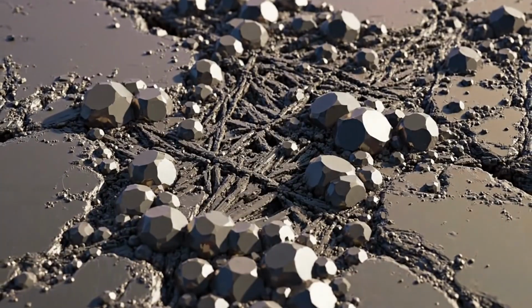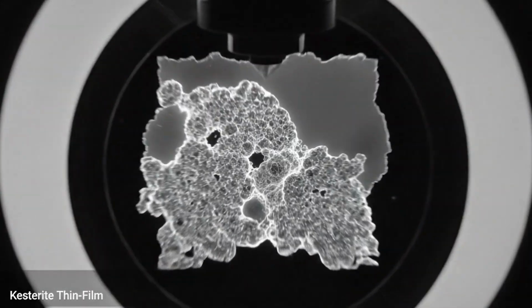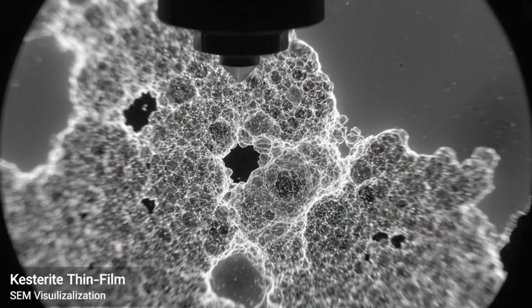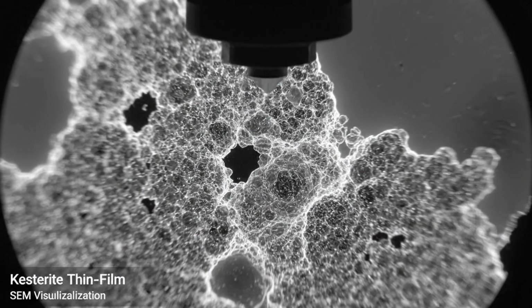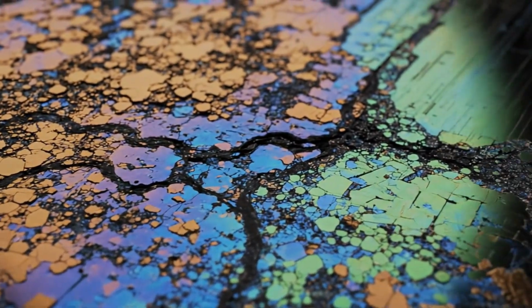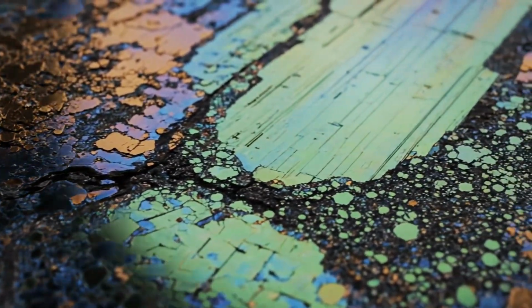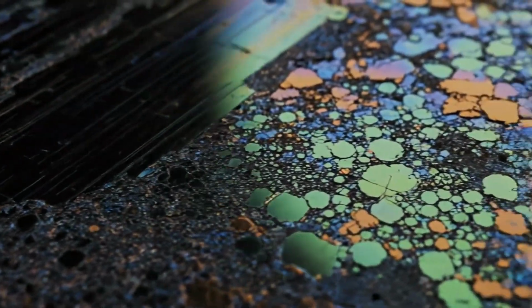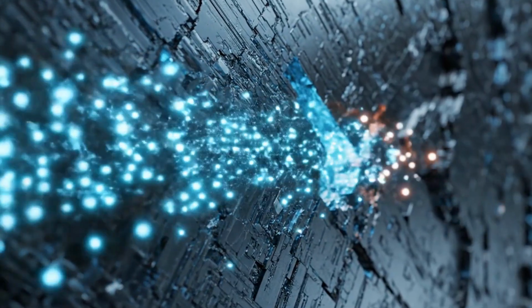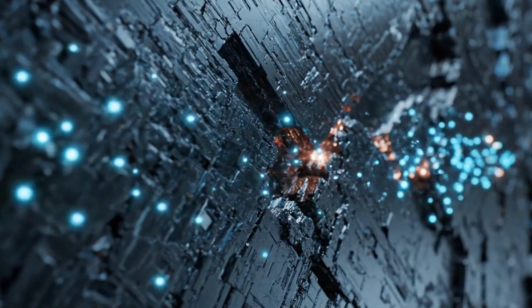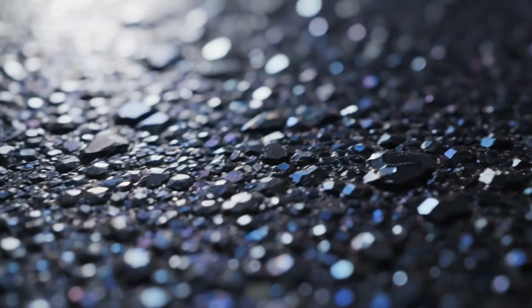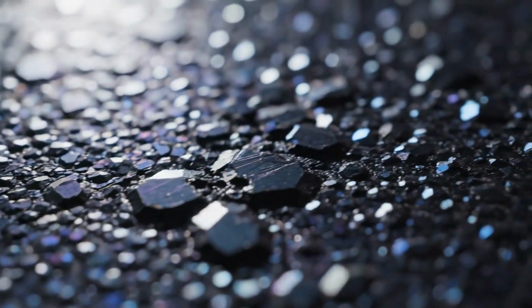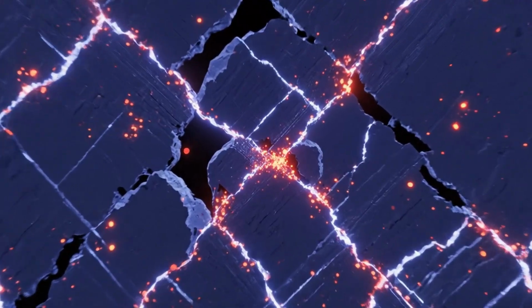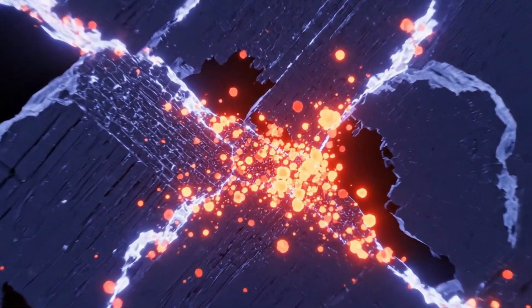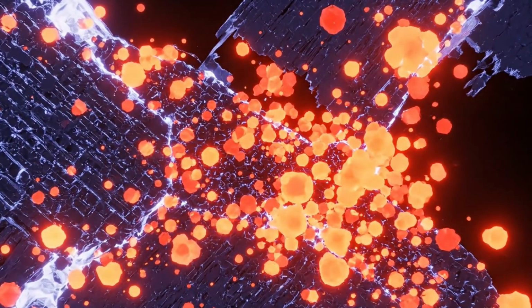These misplaced atoms create what researchers call deep defect traps. They act like potholes in an otherwise smooth road, catching electrons before they can escape. And once electrons are trapped, recombination becomes far more likely. The problem doesn't stop there. Kesterite crystals can also contain vacancies, missing atoms in the lattice, which further disrupt electron flow. And at the boundaries between kesterite and the other layers in a solar cell, mismatched interfaces can introduce even more traps. All of this adds up to one result. Real-world kesterite cells perform far below their theoretical potential.